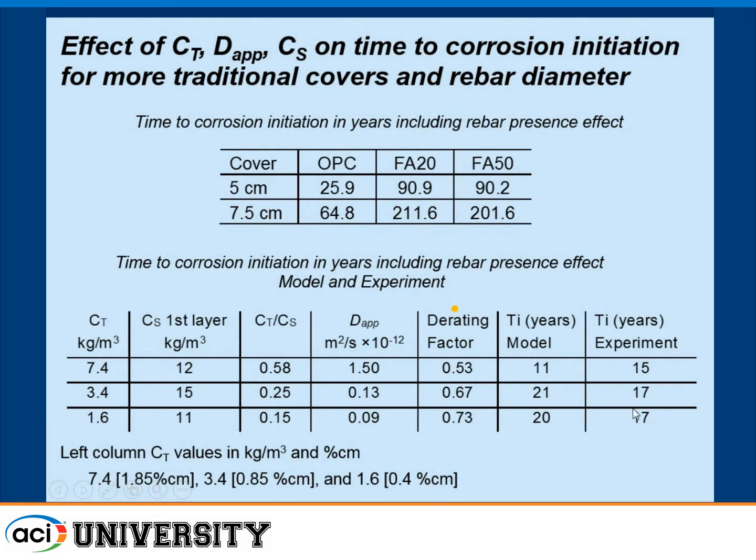And then we validated the measurements that we obtained, and we found that if you use the derating factor directly, we, in some cases, predicted a larger number of years, and in others, a smaller number for the case of the OPC. And the reason for that is that the concrete is heterogeneous, so that was not considered, and also, exposing it to seawater, there might be some calcareous deposit that starts forming and might modify how the chlorides are transported at the initial layer.